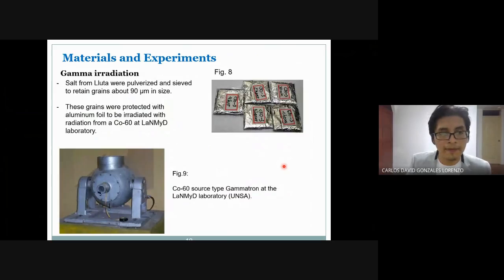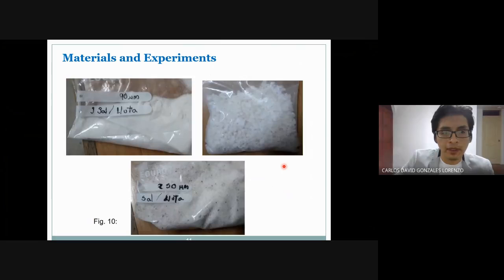For gamma irradiation, salt from Lluta was pulverized and sieved to retain grains of about 90 micrometers in size. These grains were protected with aluminum foil to be irradiated with radiation from cobalt-60 at our laboratory. This cobalt source is a Gammatron type, used for the irradiation of samples, in this case salt from Lluta. Okay, we can see the salt of Lluta in different sizes for different purposes. For TL measurements, we use these grains of about 90 micrometers in size.